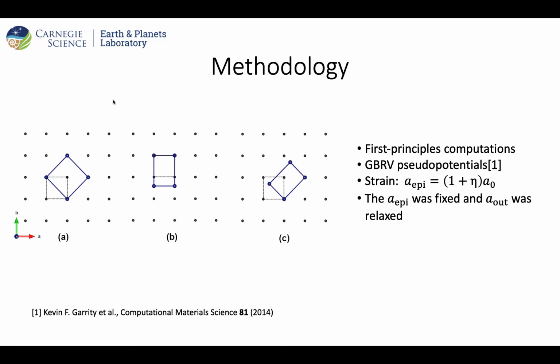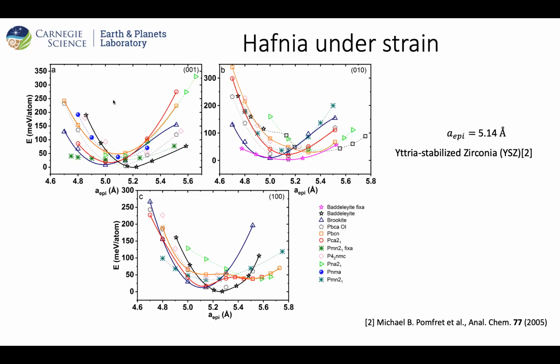We use first principles computation, mainly with the GBRV pseudopotentials. We apply strain by constraining the epitaxial lattice constant to a certain value, and we allow the out-of-plane lattice constant to relax, and also the atomic positions. Performing those calculations, we considered three different orientations: the 001, so the Z direction is out of plane, for panel A. For B it's the 010, and for C it's the 100.